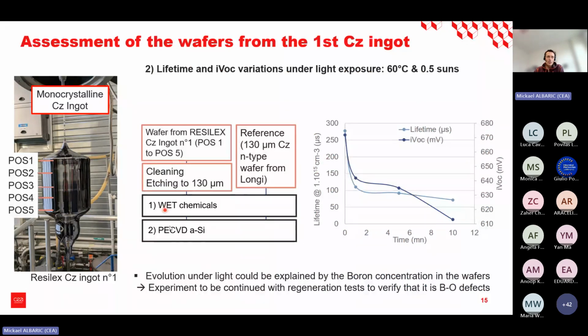We also performed another set of experiments. This is a lifetime evolution under light exposure. So we took some wafers with the amorphous layer passivation, and we put these wafers under 0.5 sun of illumination and at 60 degrees C. Why did we do this? It's because these conditions are typically the conditions of PV modules when they are working. And you can see here, it's very interesting to see that the lifetime of these wafers strongly reduces with time under illumination and temperature.